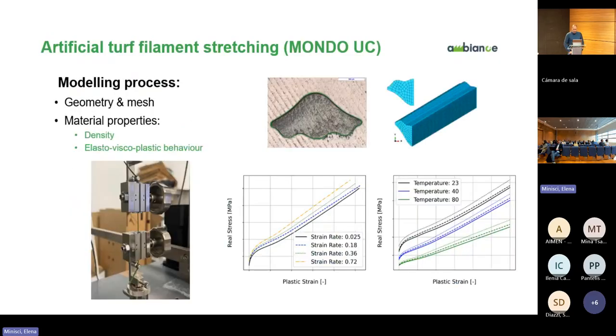So more or less, I'm going to follow the same scheme for all the use cases. Some brief notes of what we are doing here to develop these models. First of all, we need a geometry. In this case, we are taking the filament cross-section just after the extrusion, and we convert this into a finite element mesh to be used in the process. Probably the most interesting thing here is to characterize the material behavior, because in this case we need to perfectly reproduce the viscoplastic behavior of the material. That means we need to characterize it at different strain rates, which are typical of the velocities we have on the godets of the project, and also the dependence on temperature.